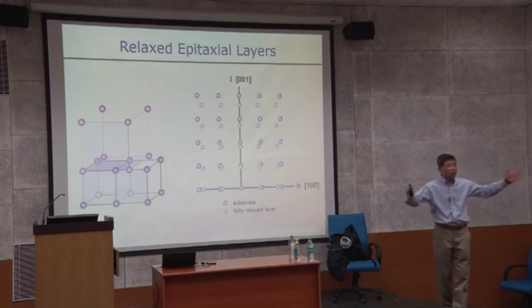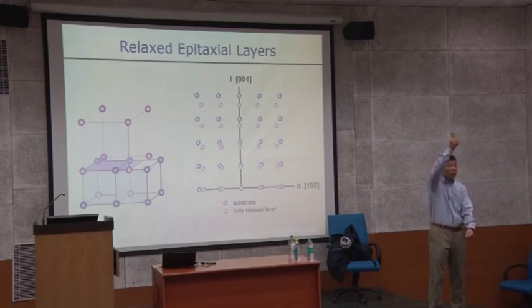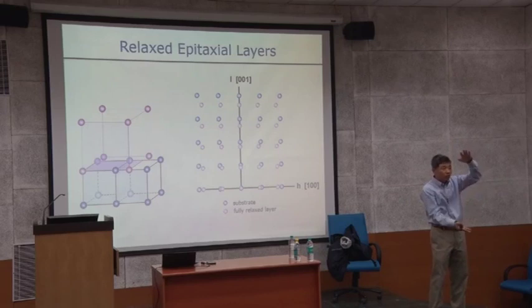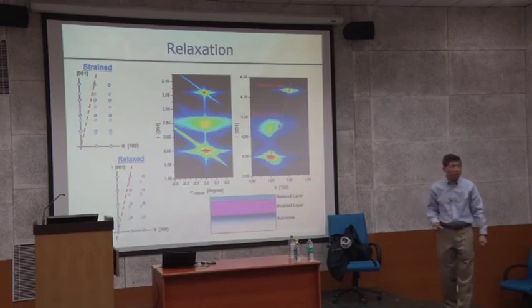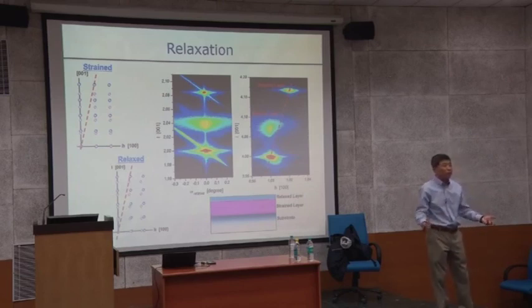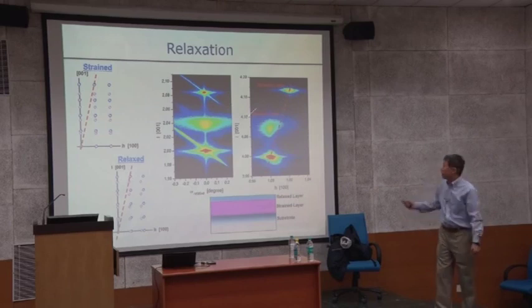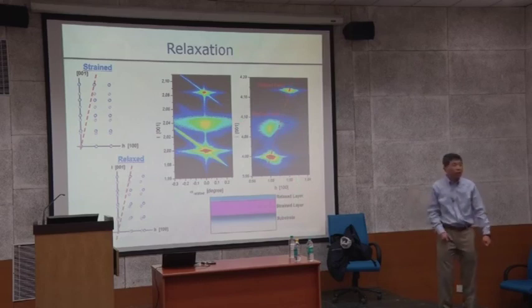In the compressive case, you're elongated, and the tensile case actually shrinks. So from this, if the distance changes from shorter to longer, you can immediately tell compressive and tensile too. You understand that? Also, at the same time, from this position you can also tell.